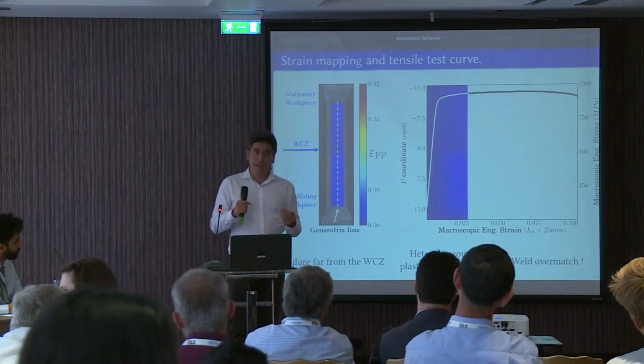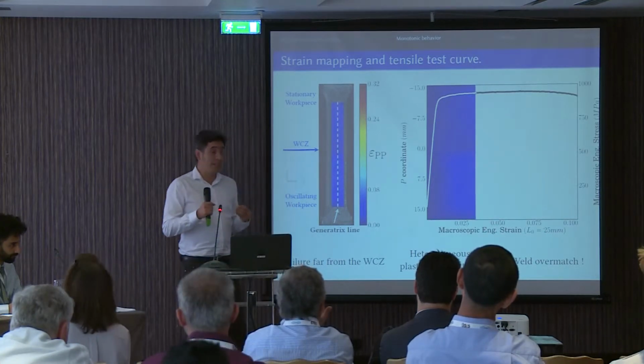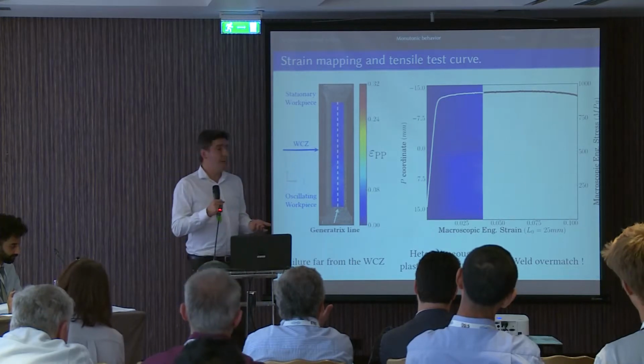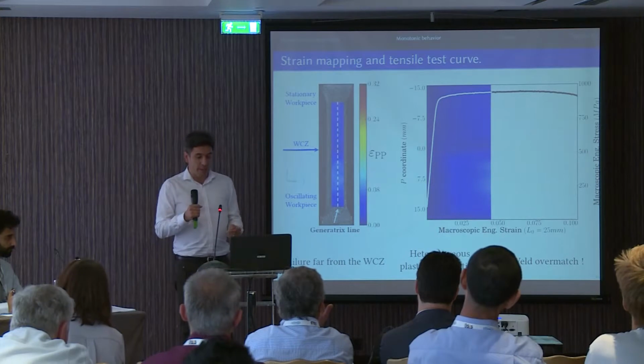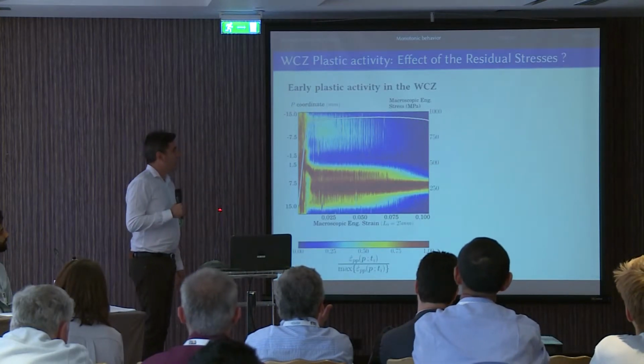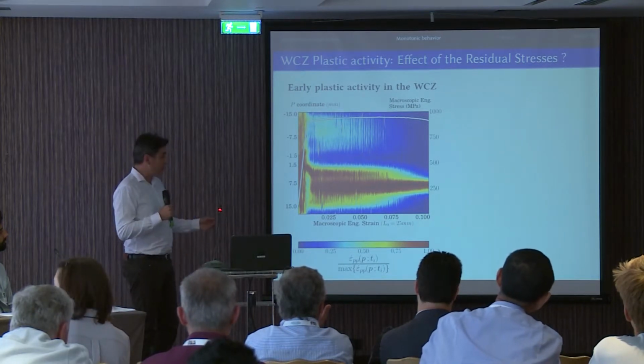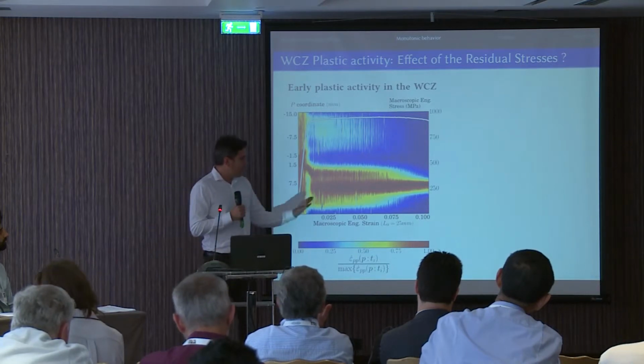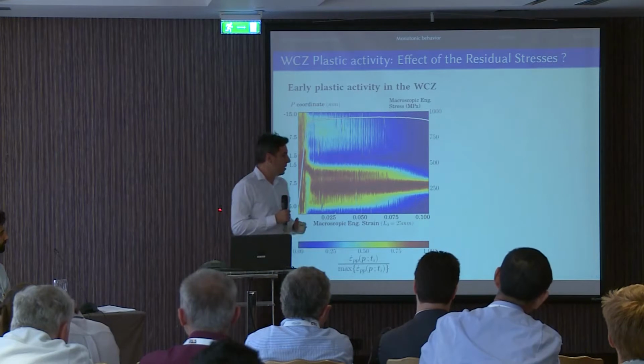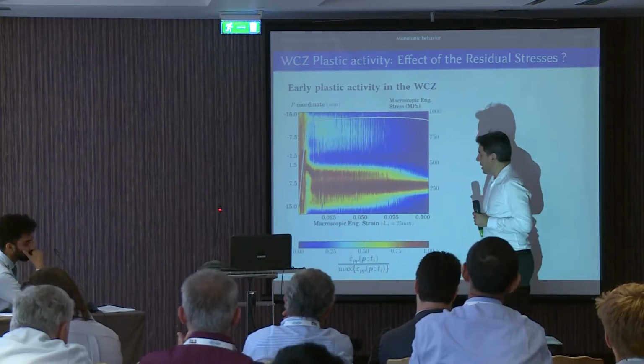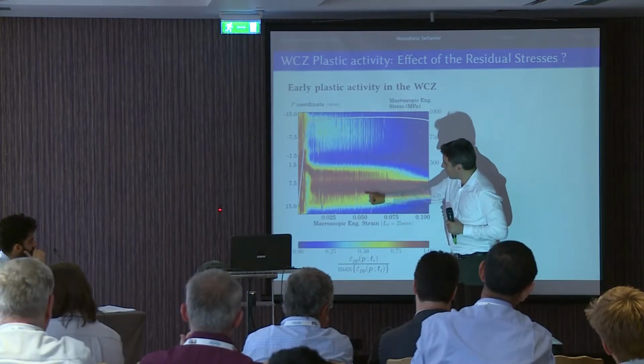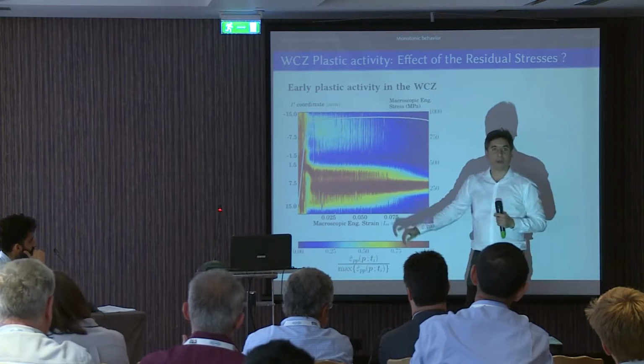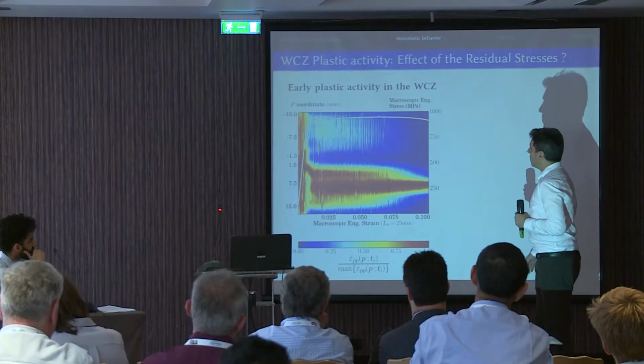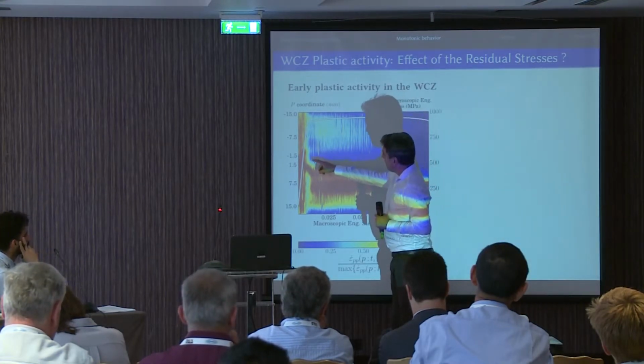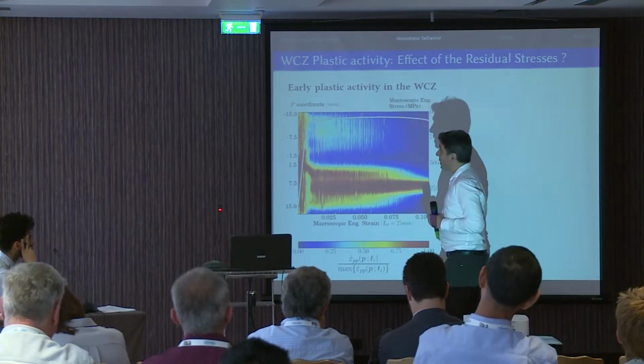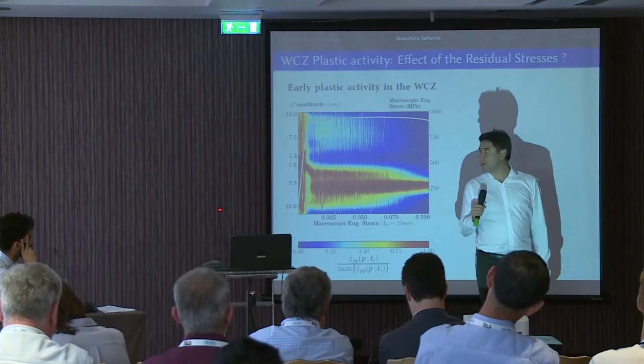This information shows us the accumulated strain. But if we were interested in studying the instantaneous activity, we should take another variable. Which variable should we take? Well, of course, it is the strain rate. Here we have, once again, the spatial temporal graph for the strain rate. Please notice that I have normalized the strain rate by the maximum strain rate on every line. For example, when the macroscopic engineering strain is 0.05, the maximum strain rate is located at more or less 10 millimeters. So we confirm once again localization, well, overmatch. But if you take a look somewhere here, when we quit the elastic domain, some activity is observed at 1.5 millimeters away from the weld.